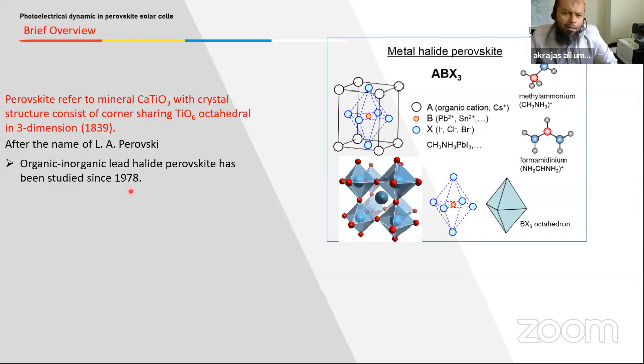And in 1978, the sister of the oxide-based perovskite, namely halide-based perovskite, was discovered. And since this time, this material has been widely explored due to its interesting physical and chemical properties. And as we mentioned earlier, their application in solar cells was reported in 2009. In principle, the monovalent cation sublattice can be replaced with any cationic molecule, depending on the size of the molecule, if it can fit into this cavity, so we can use it. If the molecule is big in size, it may destroy the structure and induce a phase transformation of the perovskite.